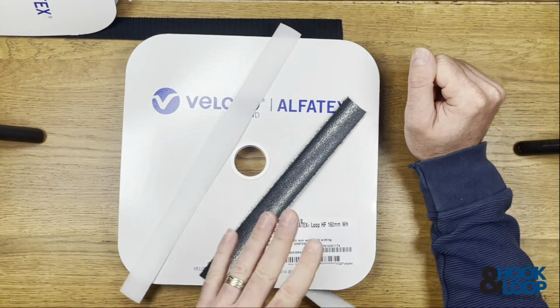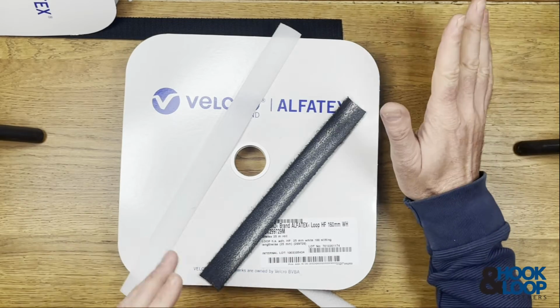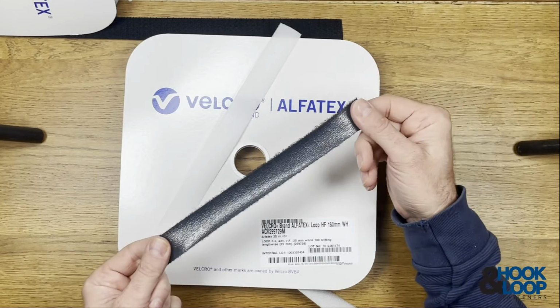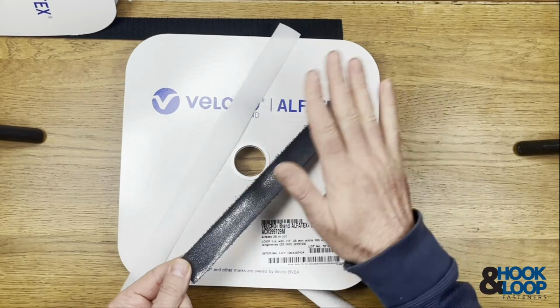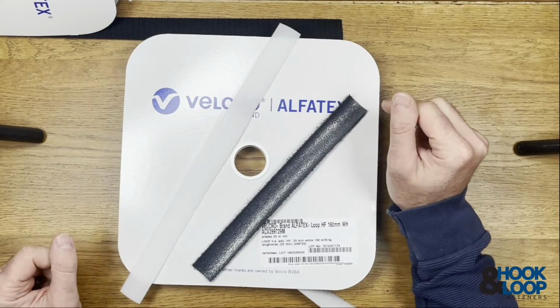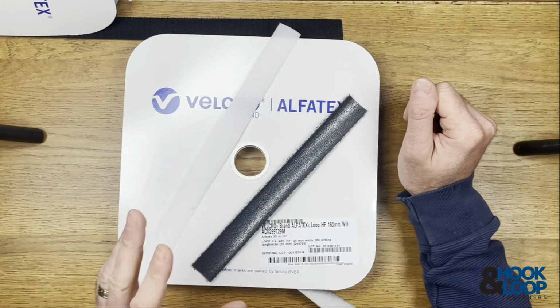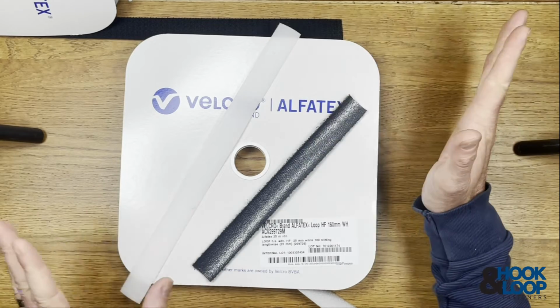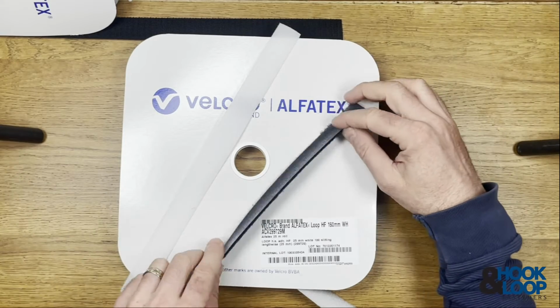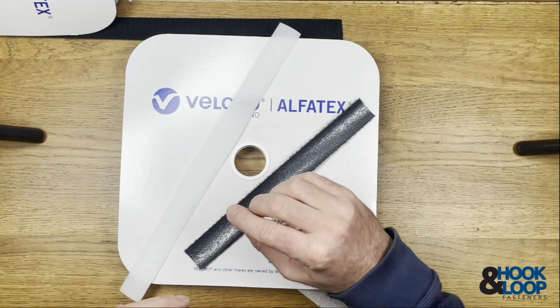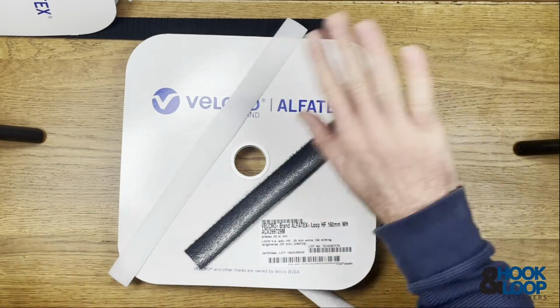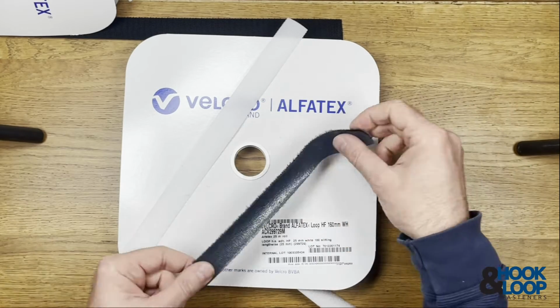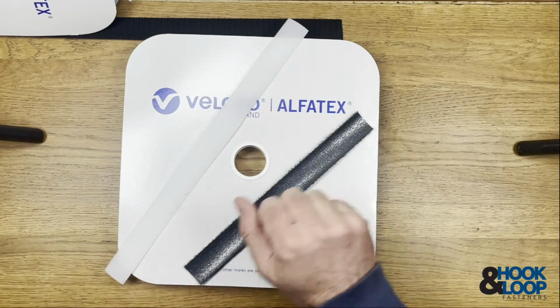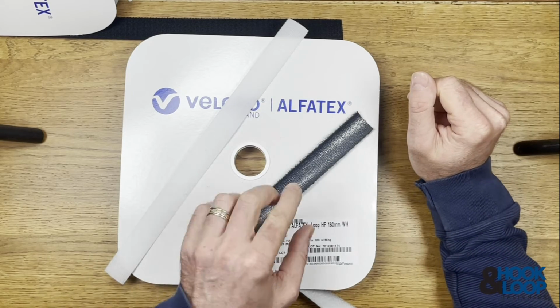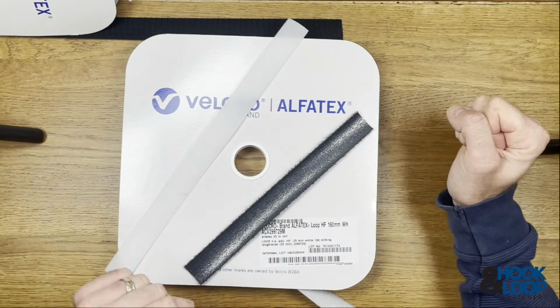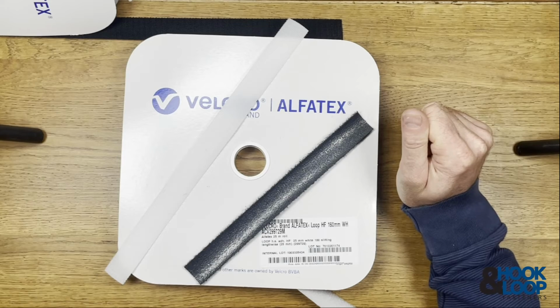This is no steam. So you have the steam iron turned off, the iron on its hottest setting. It needs to be over 100 degrees to activate the adhesive properly, but not over 200 degrees. So if you were using a heat press, provided it was over 100 degrees and not over 200, you would be fine. Other than doing away with the steam iron, the application is the same. You lay this face down onto the board, you put your fabric over the top, and you iron through. It will work on any fabric that has no stretch, and it works very well.